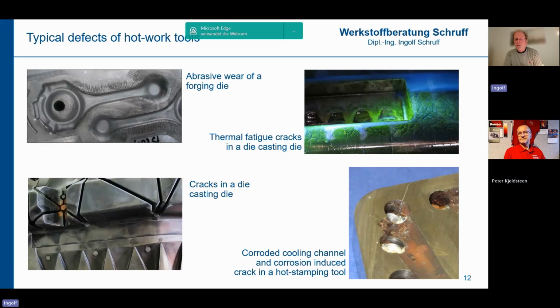Yeah. The other thing is that nowadays we have also a lot of die cast components in the cars which have visible surfaces and aesthetic surfaces. That means the requirements are extremely high because nobody who buys a modern car wants to see traces of thermal shock cracks on the visible cast components. Yeah. And you also have mounting surfaces in these cast components. And if you then have a burr as the trace of the crack on the casting, then mounting these parts into a car would be difficult. Yeah.